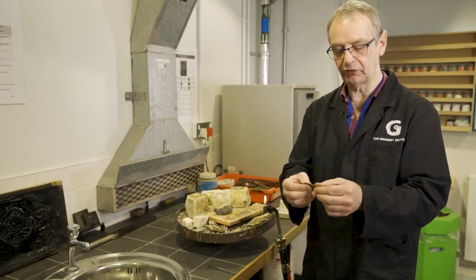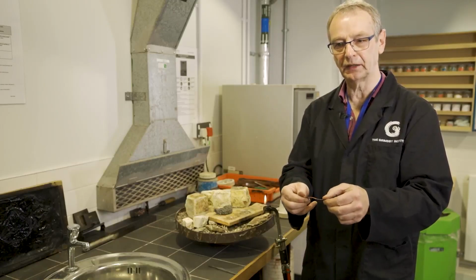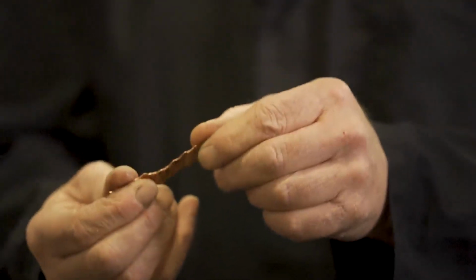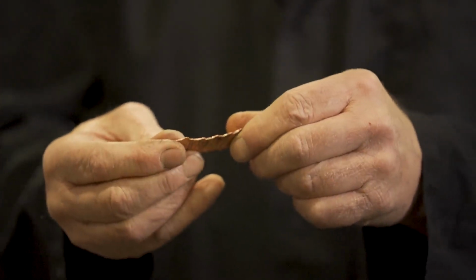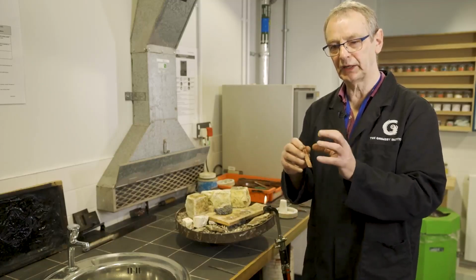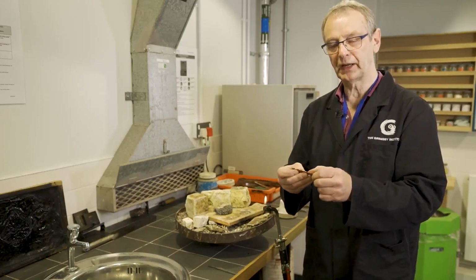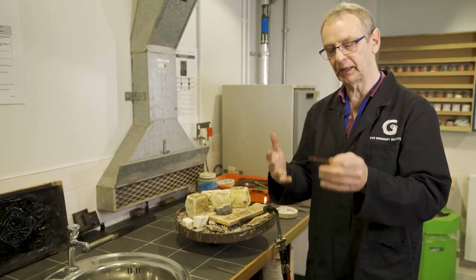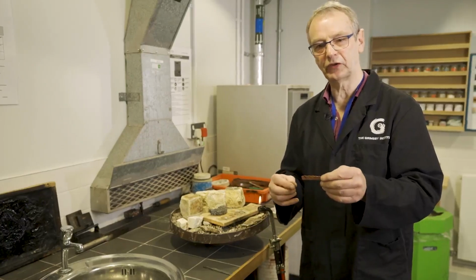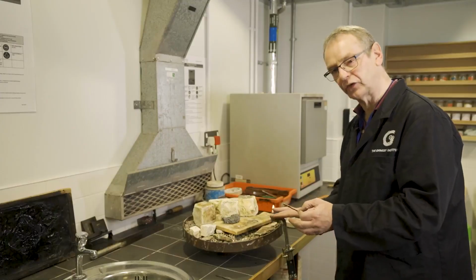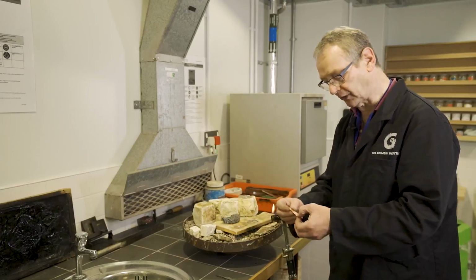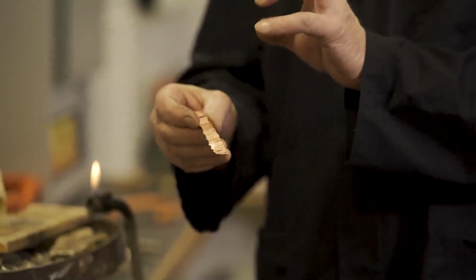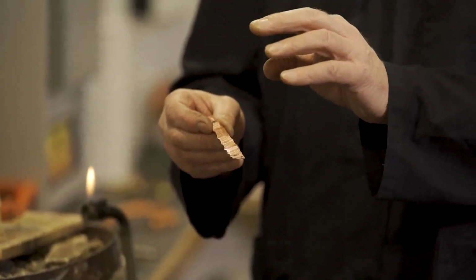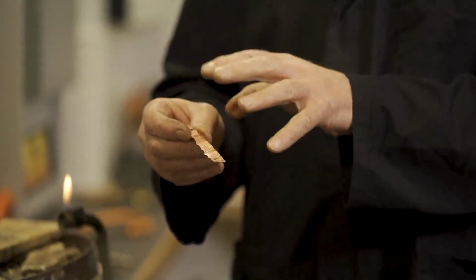But if we continued to bend it, then it would become work hardened again, and we would have to anneal it again. If you were raising a bowl or making a complicated shape, then you may have to do the annealing process maybe up to 20 or 30 times. What happens when we heat the metal up, especially copper and silver, is they oxidize. It's a reaction between the oxygen in the flame and the atmosphere reacting with the copper, and silver has a small content of copper, so the copper oxidizes.